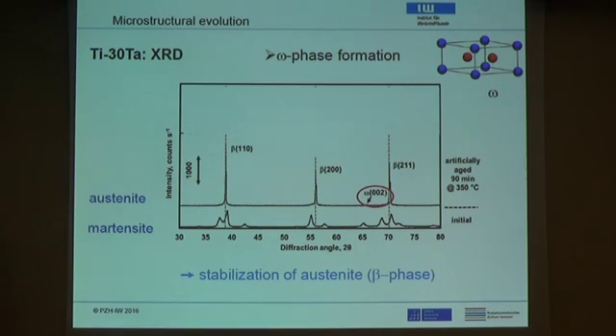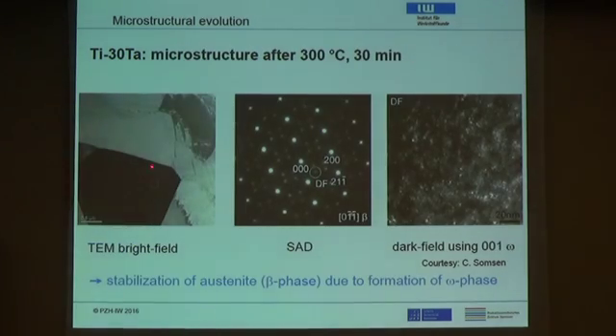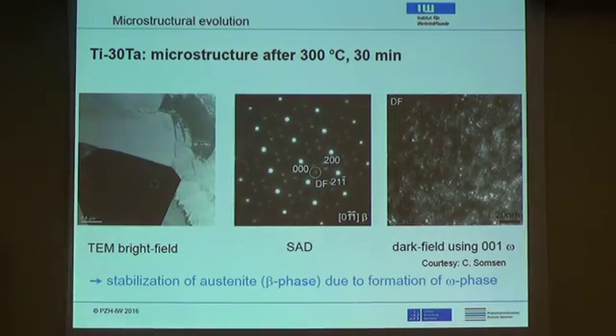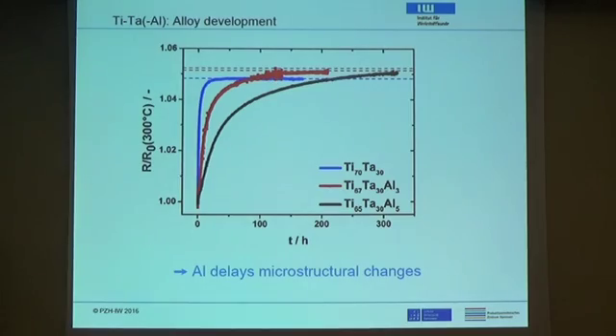The omega phase is much, much easier to see if you do TEM. These are TEM images. Here, these background speckles, that's the omega phase. And if you do selected area diffraction, you get these extra peaks in here. And if you pick one of those reflections and you do a dark field image, then you can see the omega phase, which is these tiny bright particles here. So the omega phase has a size of around 1 nanometer or so. And it's the omega phase that stabilizes the austenite, which basically degrades your material. So you need to do something about the omega phase.